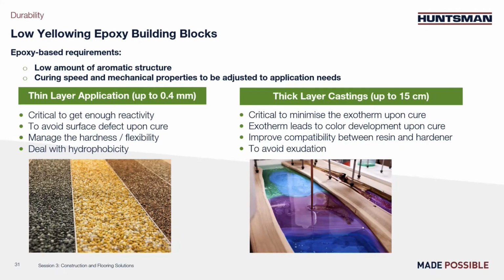Low yellowing. Here, as we've shown before in the first part of the presentation, the epoxy systems are subject to UV exposure, which often leads to yellowing. As discussed earlier, it's possible to minimize the yellowing when you choose the right building block, not aromatic, but it's also important to tune the other parameters, reactivity, and so on.